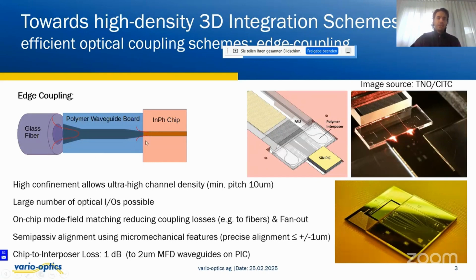Now, usually with edge emitting devices, alignment is very critical and often uses active alignment. We think passive alignment, or at least semi-passive alignment, is the way for high volume production. We demonstrated that using micromechanical devices and visual-based pick and place tools with alignment precision better than ±1 micrometer, and we get insertion losses from chip to interposer of less than a dB. Of course, we also have some losses on the glass fiber side, but if we go from glass fiber to indium phosphide or something else, that will still have higher losses there.